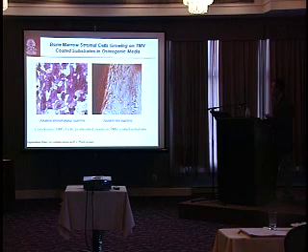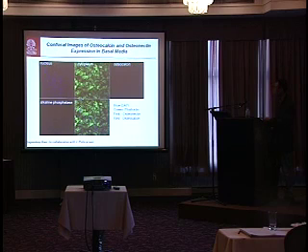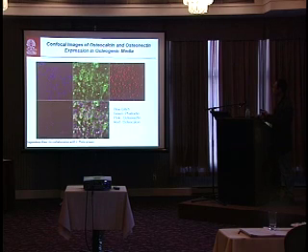To make the long story short, Gagan Deep in my lab, in collaboration with J-Pulse, can see our scaffold is biosafe, and based on very simple RGD modification, we can have the cells grow on the surface. This is the alizarin red staining. The red color shows we have calcium. In other words, we can already translate from stem cell to the final osteoblast. Very nice. There is also confocal microscopy. Let me show this one.